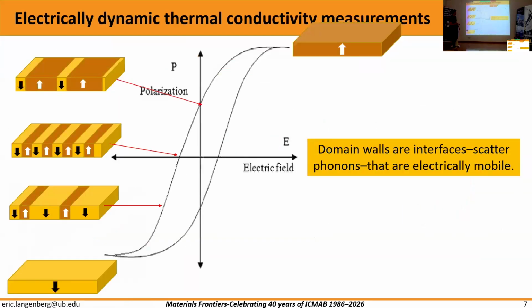And one way is using a ferroelectric material, because ferroelectric materials have intrinsic interfaces, domain walls, that can be moved with an electric field. So we can polarize with an electric field, remove all the domain walls, and have a single domain, and with a single domain with no interfaces, the thermal conductivity is going to be high. And with a large number of interfaces at the coercive field, it's going to be low thermal conductivity. And then we can change that with an electric field.